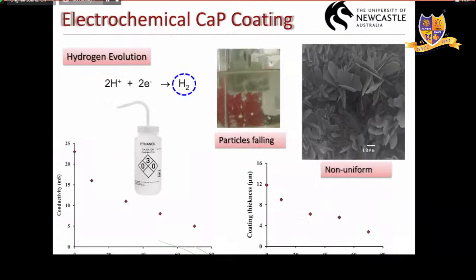So we did some calcium phosphate coating on magnesium, on pure magnesium. But surprisingly, we saw that the coating adhesion was very poor. As you can see, this is just a photo of a coating on a magnesium alloy. You see these particles falling down. The coating is not adherent to the sample.